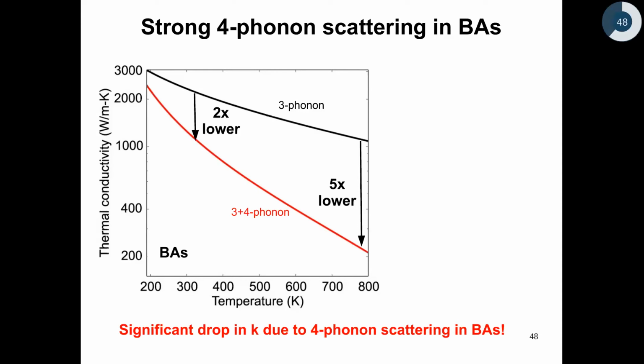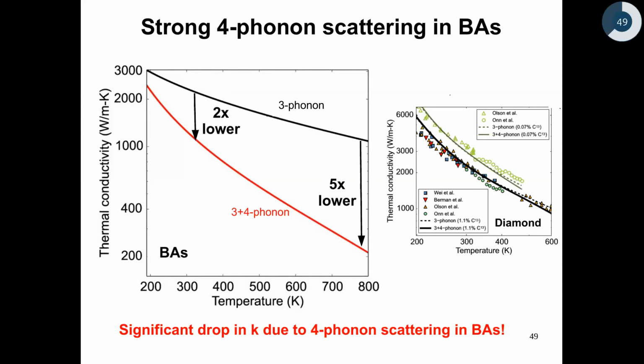So clearly, there is a significant drop and an effect of 4 phonon scattering on the thermal transport in boron arsenide. Before I proceed, if you remember, I had mentioned that for diamond, we expect 4 phonon scattering effect to be weak because we were able to get excellent agreement with the experiment with just the conventional 3 phonon approach. And that's basically what we get.